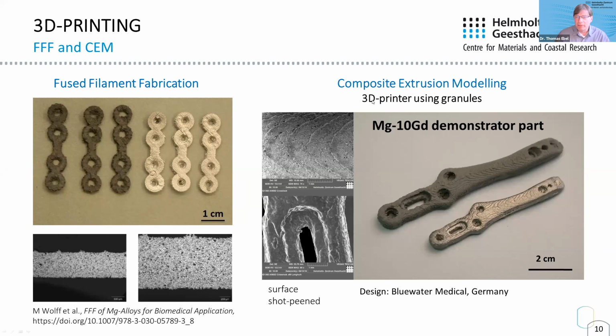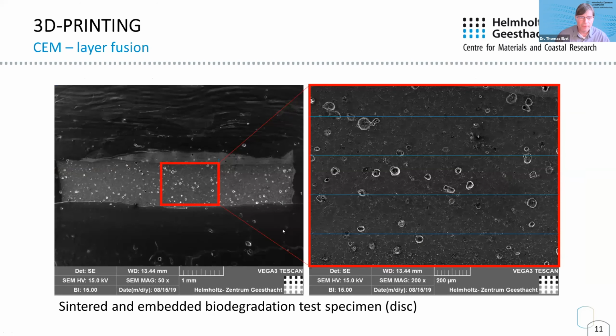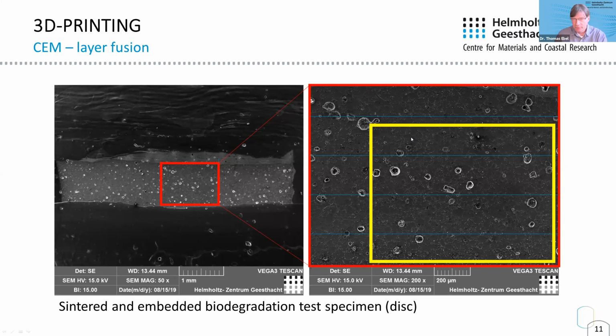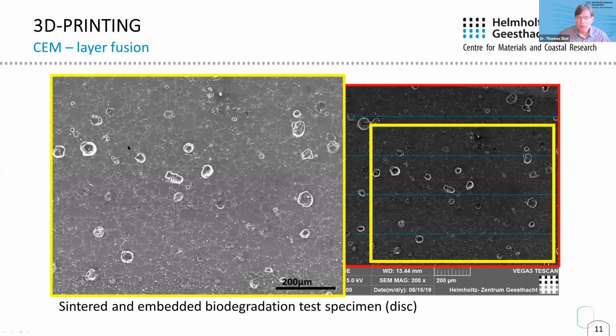And we also applied our 3D printer, which is using granules, so the composite extrusion modeling, and we made a different part from a different alloy. And you can see that it's, again, not really perfect, but it works. What is really nice is that if we make a cross section through the material, we can look for the fusion zones again. So, can we see where the layers were? These blue lines here mark the previous printing layers, and we can go to a little bit higher magnification. We can see now we have really a homogeneous material. So after sintering, we have one material, and we don't see these printing layers. As I said, there's much room for optimization.